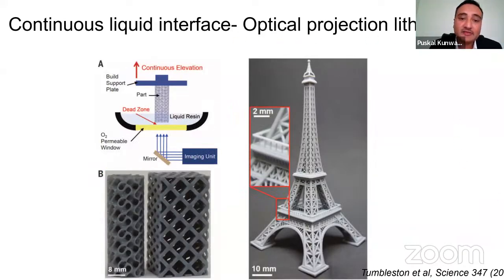One form of optical projection lithography, which is a widely used technique now, is CLIP. The company Carbon is completely based on this technology. How this works: you have a vat filled with liquid resin, and there's an oxygen permeable window here. The oxygen permeable window makes a dead zone just above the window, so that the printed part does not stick to the base plate. There is always a small gap, because oxygen kills the radicals responsible for polymerization.